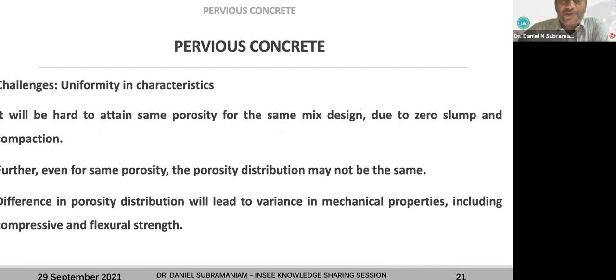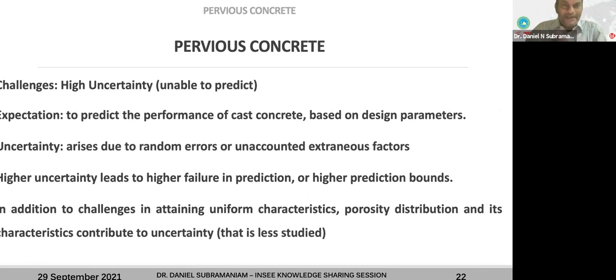And so even for the same porosity, the porosity distribution may not be the same. For example, we may have all the different mixes happening at the same time. Even in your experiments, you might be able to get the same porosity, but you might have different compressive strength because the porosity distribution is not the same, right? So a difference in porosity distribution will lead to variance in mechanical properties, including compressive and flexural strength.